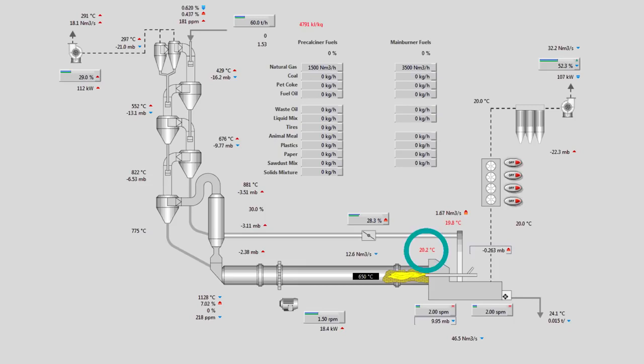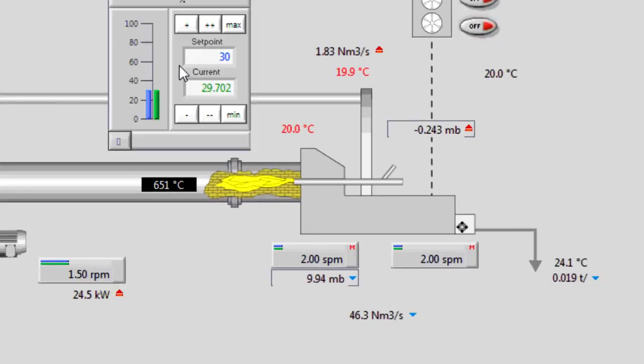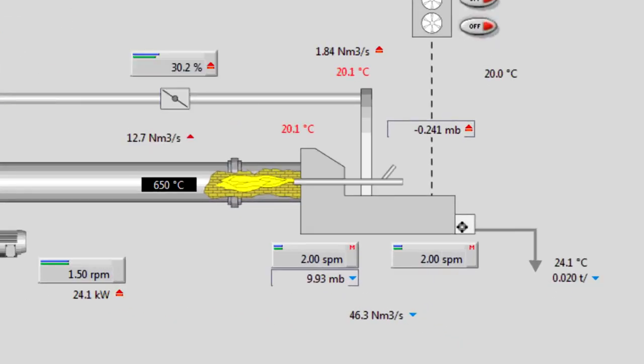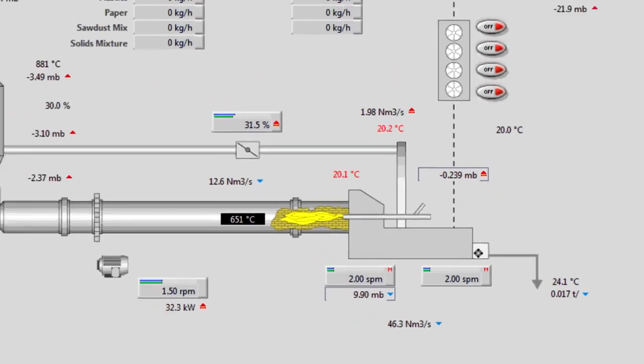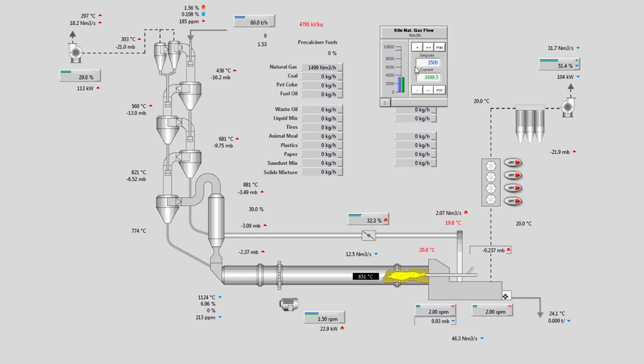You notice that the secondary and tertiaries are very low. Clearly, the clinker cooler is empty and we're pulling ambient air into the system. You also see a cool burning zone. This is normal because the pyrometer is pointing below the flame and there's no material there at the moment. More fuel at main burner.